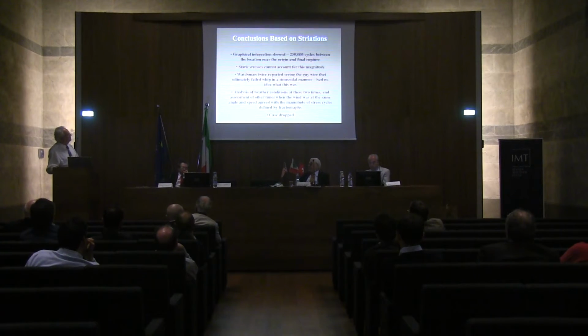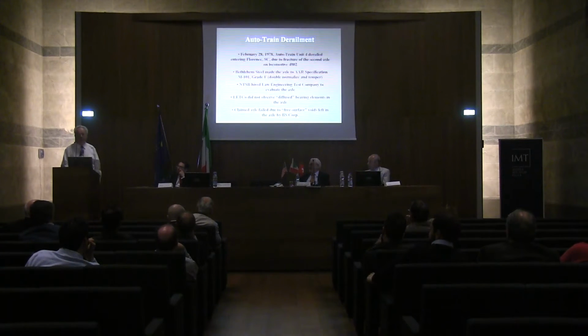The analysis of the weather conditions at these 2 times and assessment of other times when the wind was at the same angle and speed agreed with the magnitude of stress cycles defined by fractographs. And the result was, when we wrote our report, they dropped the case because they recognized that they had no basis. Now I want to talk about another failure.